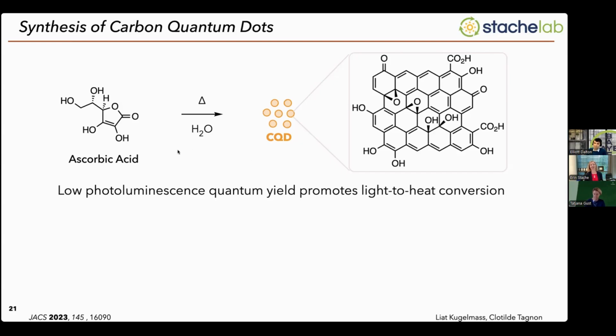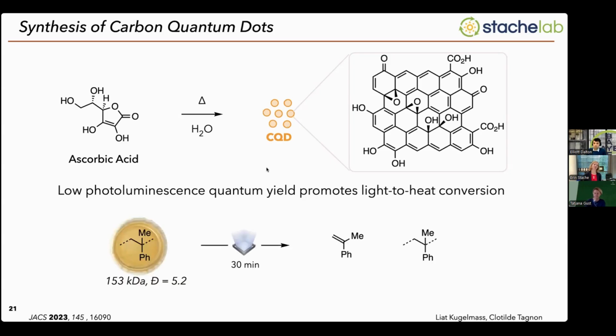So these are just colloidal carbon. We heat up ascorbic acid in water, and it generates some structure similar to this. And these were the worst materials, so they don't have any of the photonic properties that most people want carbon quantum dots for. But for us, this is a great opportunity because it's something very cheap, ascorbic acid or vitamin C. We can generate these materials, and then they'll generate these photothermal gradients so that we can hopefully induce depolymerization.